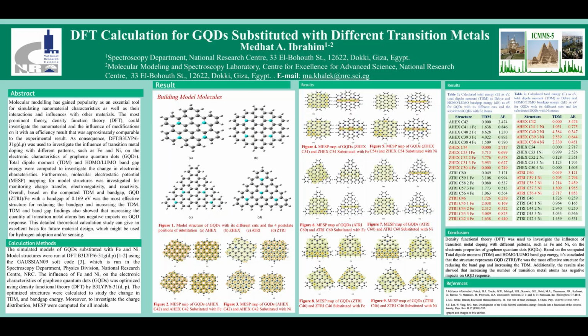Total dipole moment and band gap energy were computed to investigate the change in electronic characteristics. Furthermore, molecular electrostatic potential mapping for model structures was investigated for monitoring charge transfer, electronegativity, and reactivity. It is concluded that the structure representing graphene quantum dots in its zigzag trigonal shape substituted with iron was the most effective structure for reducing the band gap and increasing the total dipole moment. Additionally, the results also showed that increasing the number of transition metal atoms has negative impacts on graphene quantum dots response. This detailed theoretical calculation study can give an excellent basis for future material design, which might be used for hydrogen adsorption and/or sensing.